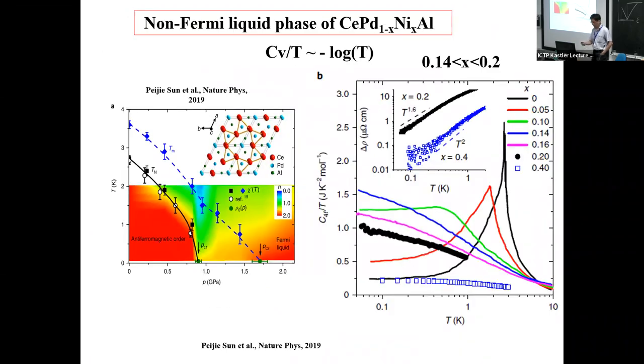Okay, and in the thermodynamics, it shows the T-logarithmic divergence of the gamma coefficient I mentioned. You can see here from these plots that they doped this material with nickel, and between 14 and 20% of doping, you can see this logarithmic divergence of the gamma coefficient. But you can see clearly from this plot that in the transport, you get two different colors, greenish and orangish, which indicates that there are two kinds of non-Fermi liquid behavior.